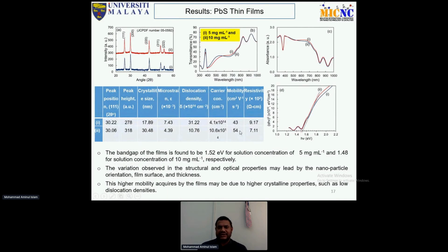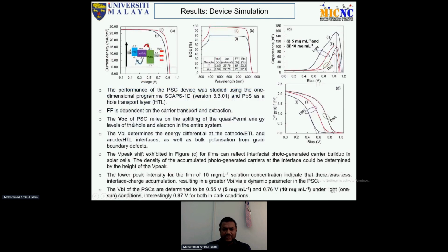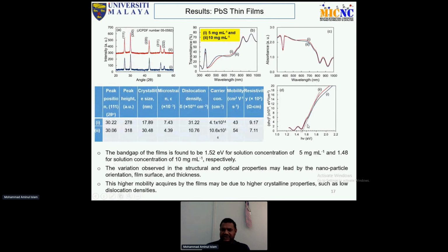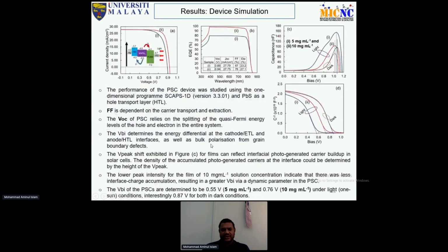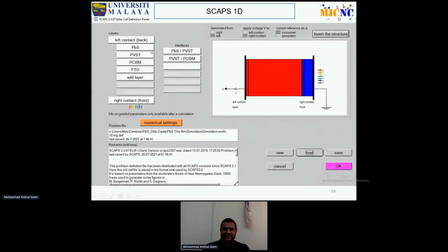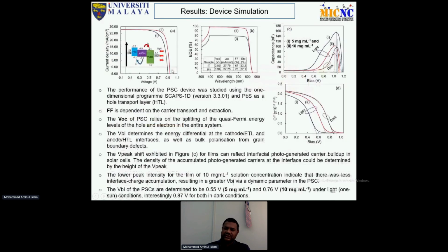Another thing is that VOC is related to the quasi-Fermi level splitting, which is related to the carrier concentration and also the band gap. We also calculated the capacitance measurement, and the capacitance is much higher for film 1. So it means that carriers are accumulated at the interface. If the interface accumulates lots of carriers, they recombine at the interface. If we lose carriers at the interface, the VOC and fill factor will be affected, which you see in the performance here.